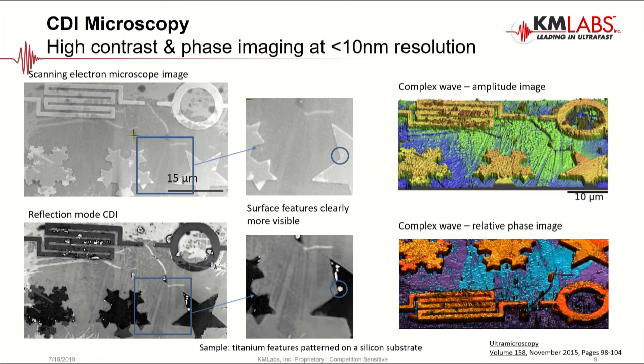And in some cases, we even get much better contrast of some of these subtle compositional variations, or what's probably foreign particles or foreign elements that have been deposited on the surface of our sample at some point during the prep or transportation process. And shown on the right is actually what we're really getting from CDI. We get two images, or two maps, so to speak. This is because we're dealing with a complex electromagnetic wave that has both an amplitude component and a phase component. When we go through this reconstruction process, we get a map of each. So we get a relative amplitude across the surface and a relative phase shift of that light. Encoded in these is information about both the composition and the height, or the topography, of that surface. Principally the composition comes mainly from amplitude information, and topography largely from the phase shift information.